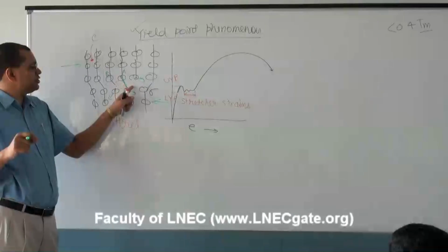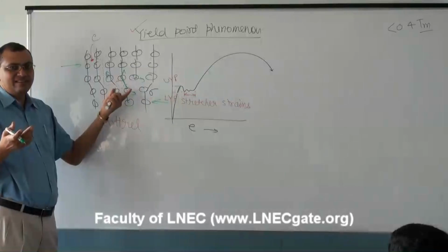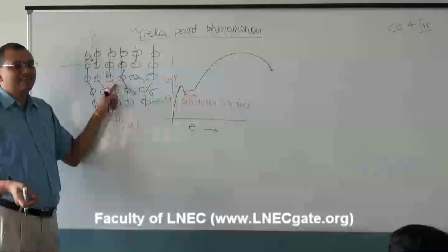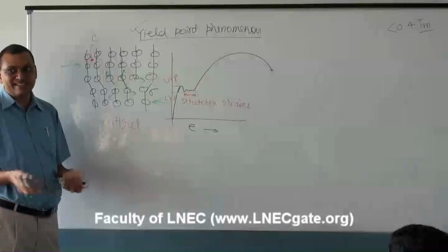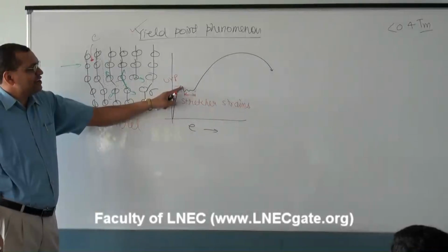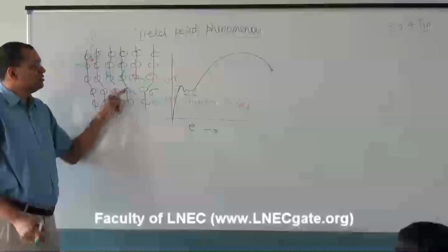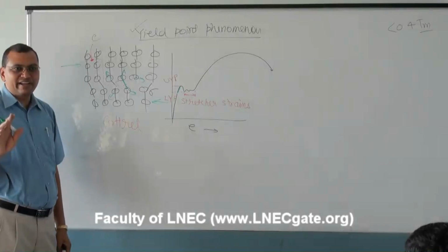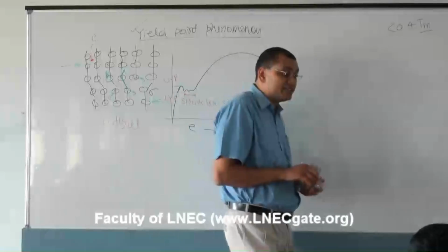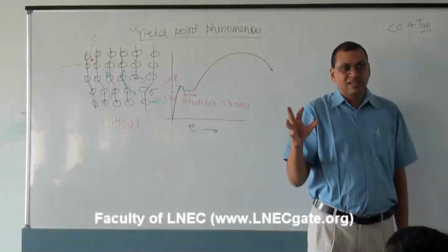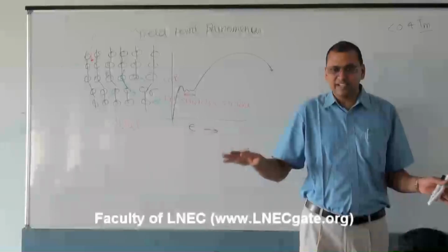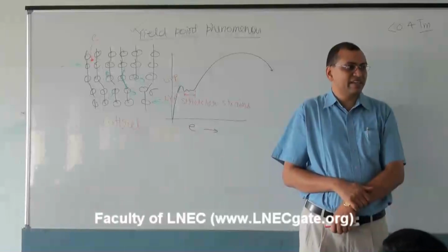But once the dislocation jumps to the new site, there is no Cottrell atmosphere, because all the carbon and nitrogen is packed here. At the dislocation site there is nothing. So slightly lower stresses will be sufficient to keep the dislocation moving. That is why the lower yield point and the yield point phenomenon appear in the material. Because you have already stressed the material to a slightly higher value, but to keep the dislocation moving, you require lower stresses.